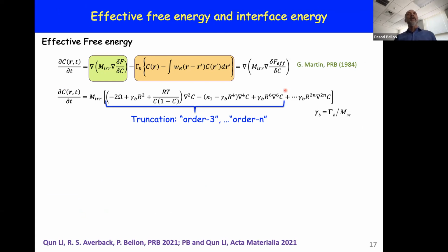How to make a connection with an equilibrium system? Well, there's an approach that Georges Martin proposed in 1984 for a related case, where he asked: would it be possible to combine these two different contributions into one contribution that would mimic the one we know for a thermal system, but for an effective system? So instead of using the true free energy of the system, I'm using an effective free energy. And the question is what would be the properties of that effective free energy to capture this competition between the two processes.